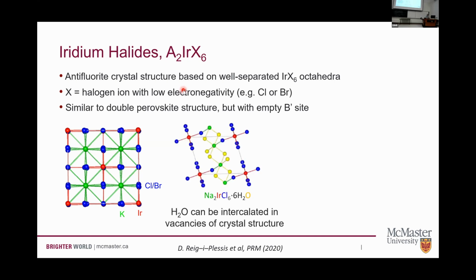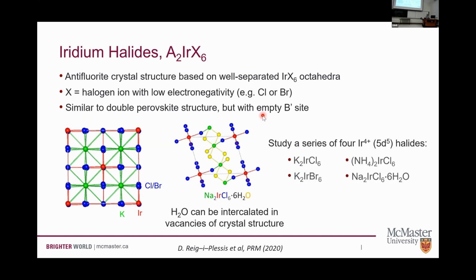We also can play some different games with this structure. We can intercalate into the vacancies that we've got here. So you can get water in between these layers, and that gives you another degree of structural tuning. And so we looked at a series of these halides. So a chloride version, a bromide version. We swapped out the potassium for ammonium over here. And then we have this sodium intercalated version here as well.